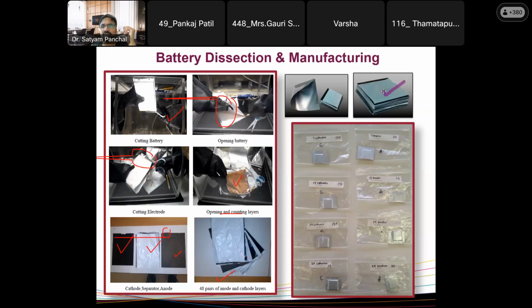So here you can see this battery. Later on, what we did is we took our own batteries and I made my 1 inch by 1 inch battery with different layers of cathode. So 7 layers, then 13 layers, then 19 layers, and then 25 layers of cathode, and the same way for the anode. And then I measured the thermal conductivity and thermal resistance of this battery, helpful for our other modeling parameters.